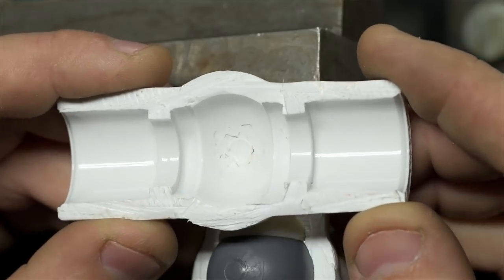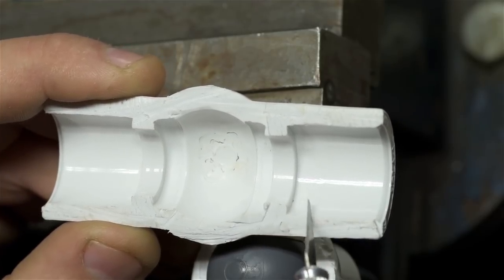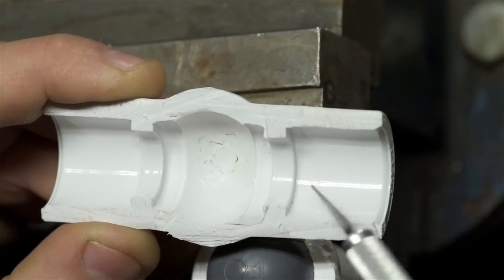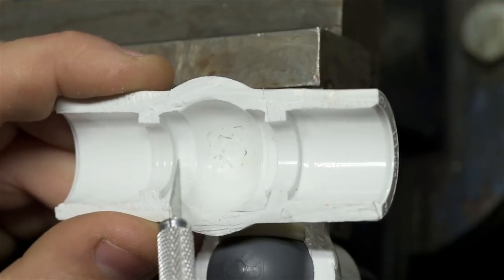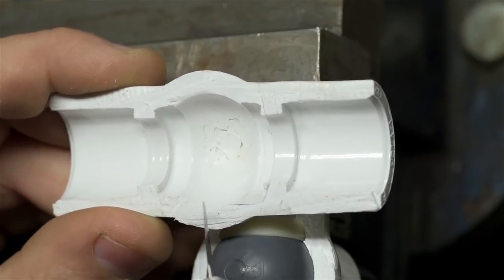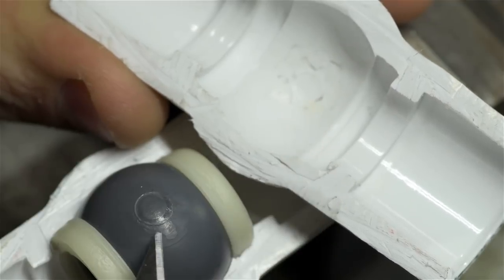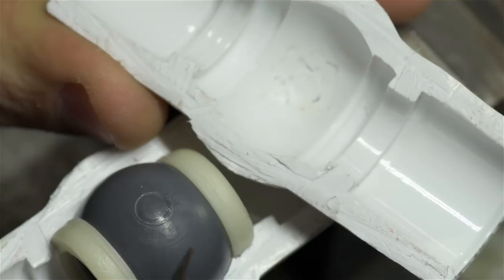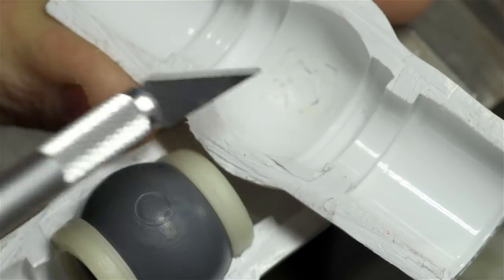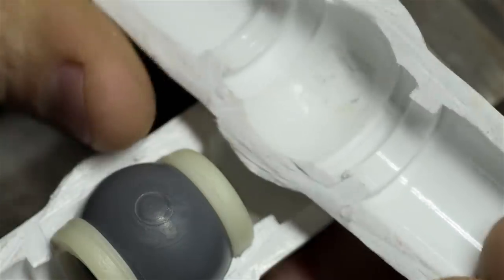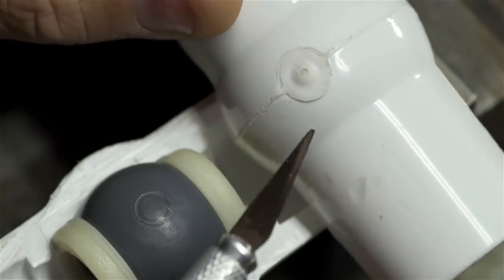I hope I'll be able to show this to you. It's quite subtle. When they injected the PVC in this case, where that molten plastic touched polished tool steel, like the mandrel that went through this to keep it all together, you may be able to see that the surfaces are very glossy. They're very bright. But where the ball and the seals are, it picked up that surface finish from those parts. More of like a matte, dull finish. If you look close, the molten PVC also picked up an imprint of the gate that was on the ball. So this ball was made in its own tool ahead of time. It was injected, just like we saw before, through a gate. Here's the vestige of that gate. It's not totally smooth, and the molten plastic picked that up when it was formed around it. There are also some wrinkles or halos around this, because again, this is where the PVC was injected. In fact, I'm willing to bet, well, let me get some calipers.